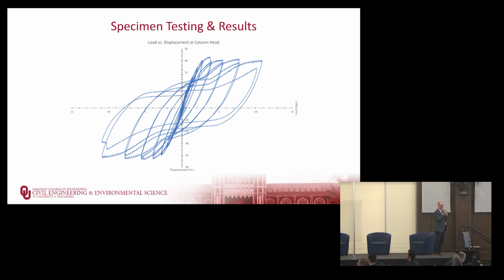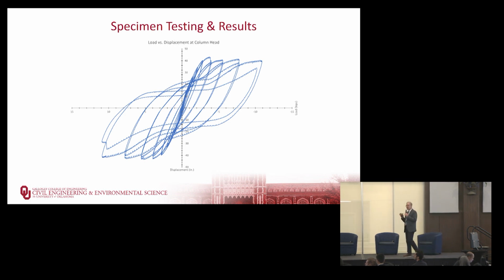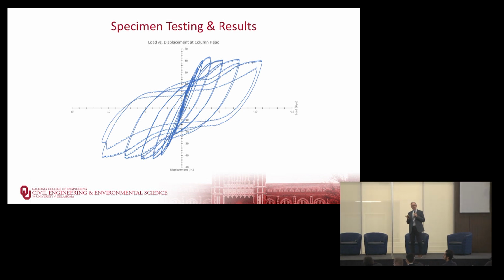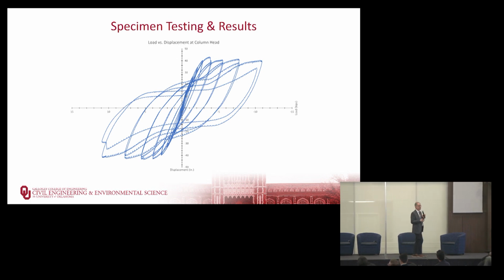So you start to yield the outside edges of the steel tube. You get more and more cycles, the displacement's getting bigger, you yield more and more of it. Eventually, you buckle the steel tube. Now, I talked about the fact that the concrete could brace the internal steel tube and the outside FRP tube to increase their buckling resistance, but it's only on one side. The steel tube can still buckle inward, but it can't buckle inward all at the same location because that would put it in compression hoop-wise. So it has to buckle in an odd shape, much different than if it was just a steel tube by itself. So you do increase the buckling resistance, but eventually that steel tube is going to buckle because you're at very, very high strain rates.